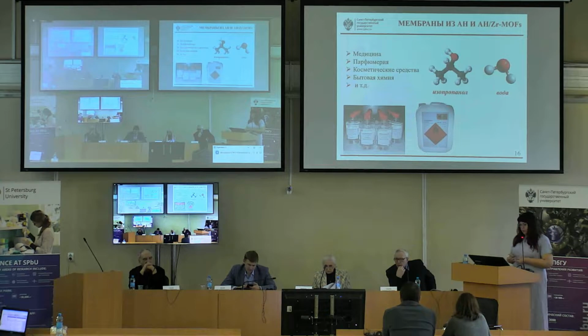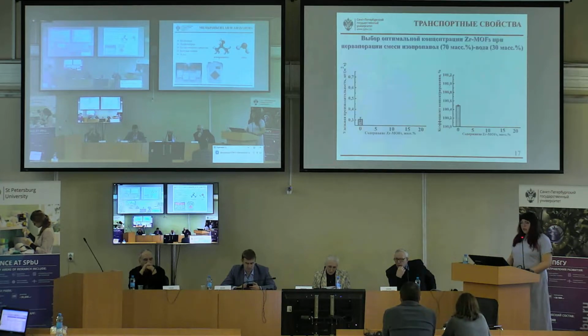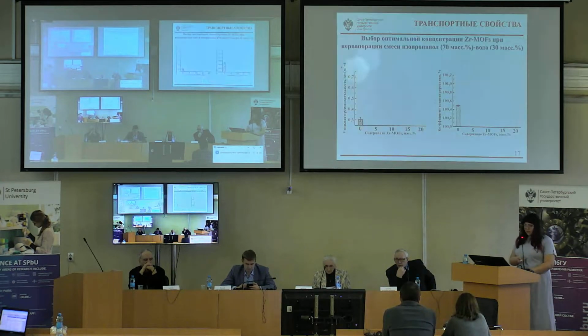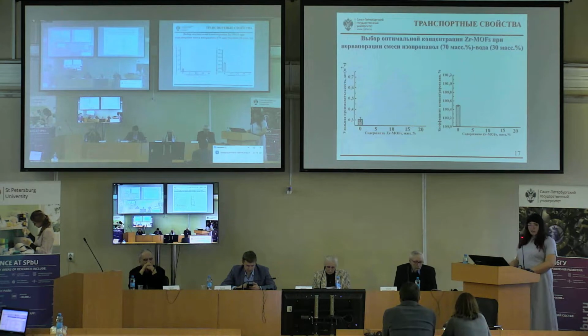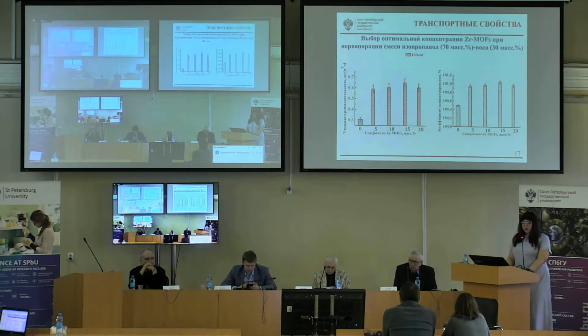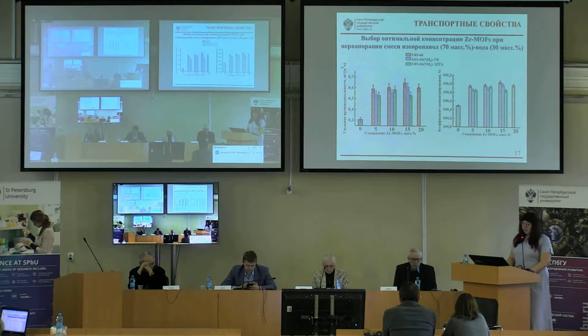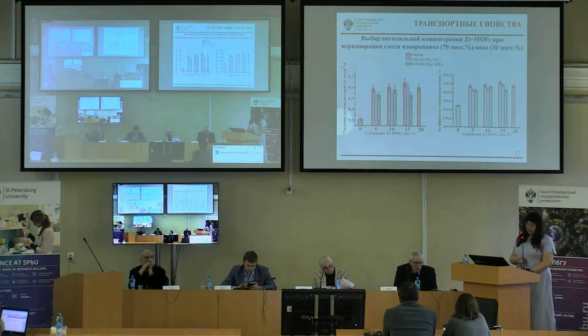The transport properties of membranes made of sodium alginate modified with organometallic framework structures were studied during the pervaporation of a water mixture. The slide shows the dependence of the specific productivity and concentration factor on the content of MOFs in the sodium alginate matrix during the pervaporation separation of an isopropanol water mixture with a water content in the initial mixture.